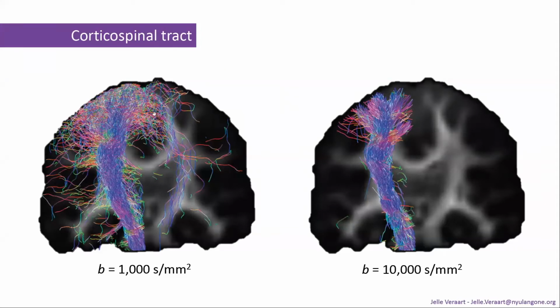Just some streamlines that I computed using publicly available software. B1000 versus B10000, and you can see that the segmentation of the corticospinal tract becomes much easier with fewer spurious fibers, in part because of the sharpness of those fiber orientation distribution functions, and mainly because of the extraaxonal space not blurring the ODF.